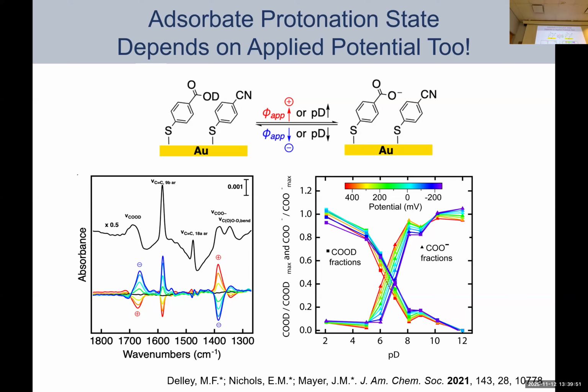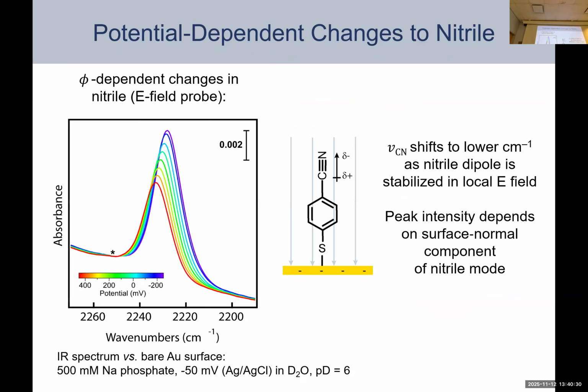We're also able to generate these sort of sigmoidal plots here, where you can correlate the fraction of protonated carboxylic acid and deprotonated carboxylate. And this looks very much like a titration curve, right? So from these data, you can actually measure the intersection point, or where both of them are essentially at 50%. It's not perfect, but decently close. You can look for 50% carboxylic acid, 50% carboxylate, and figure out at what PD that occurs. Okay, and that now will give you access to that parameter pK1/2, the solution PD at which half your surface is protonated and half is deprotonated.